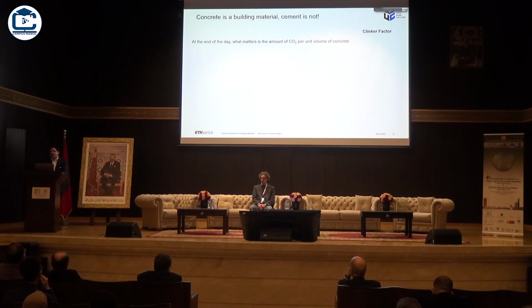And at the end of the day, what really matters if we are concerned about CO2 footprint is the amount of CO2 per unit volume of construction materials that we're putting in the field. And this certainly depends on the clinker factor. As we saw in the beginning, 96% of the CO2 is coming from that stuff that we call clinker. But also, when we start thinking about concrete, things like the binder content, how much cement per cubic meter I'm using, become particularly critical, and how much admixtures I'm using in order to control the properties of that concrete also become critical.